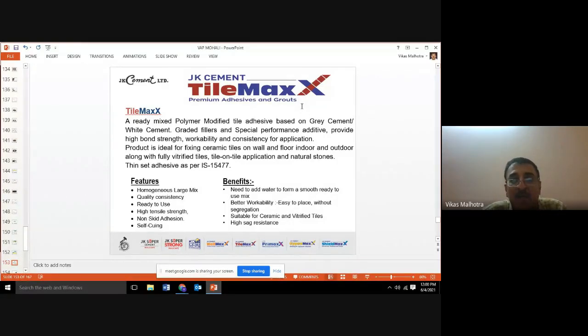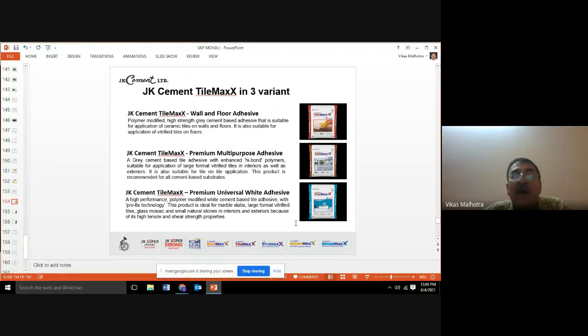And once you have put the tile, since it doesn't require any curing, there won't be any shrinkage. Since there won't be any shrinkage, there will be no issue of delamination of tiles, which normally happens with normal cement. It has some waterproofing qualities also, which will help you when you are fixing tiles, specifically in water prone areas, that is your bathrooms, kitchens or swimming pools. Now, benefits are, this is again a powder. You just need to add water, easy to apply, suitable for all kinds of wall, high sag resistance.